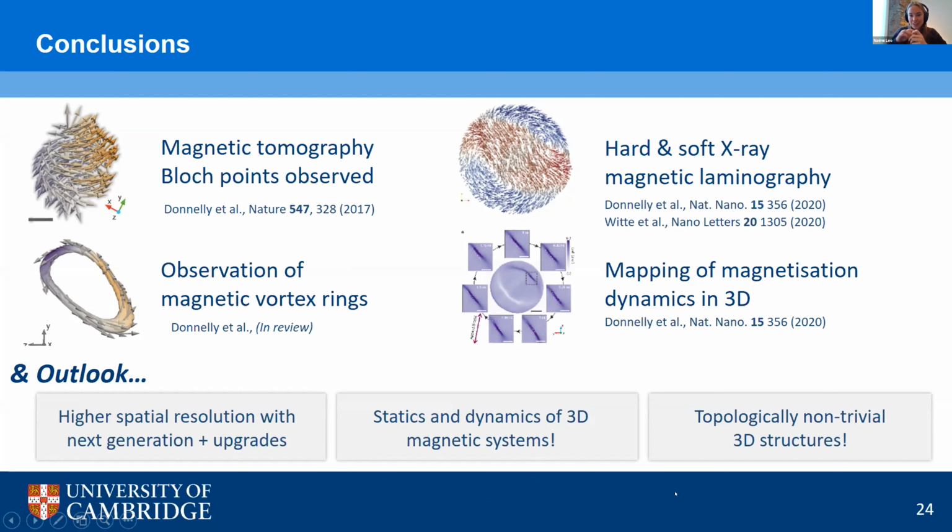So if not, then I start, because I wondered how you prepare the target skyrmion that you showed for the laminography result. So this was actually not prepared by me. It was prepared by my colleague Simone Filizio at the Swiss Light Source. The target skyrmion is a permalloy disc of about 150 nanometers in thickness. Essentially, if it was pure permalloy, we wouldn't expect the target skyrmion to exist. But the way that the permalloy grows with evaporation, it grows with a canted magnetic anisotropy. So it has slight out of plane anisotropy, and this results in the target skyrmion appearing in the structure.